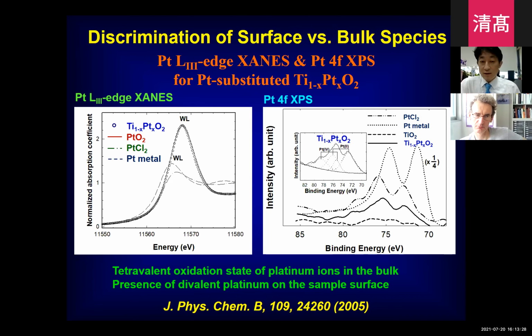But in the bulk, the substituted platinum ion is stabilized as a tetravalent state. Because on the surface there are many vacancies, normally the coordination number is lower than 6. So as you know, platinum 2+ can be stabilized in the square planar geometry or tetrahedral geometry due to the d8 electronic configuration. So it's very well matched with general inorganic chemistry knowledge.